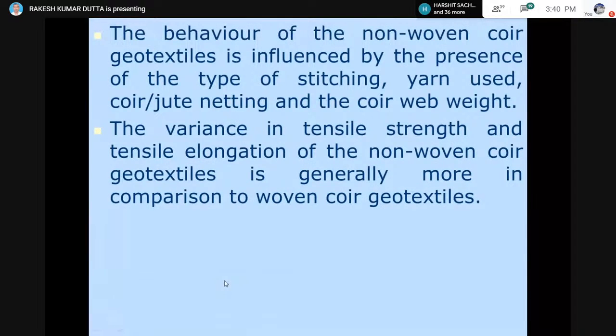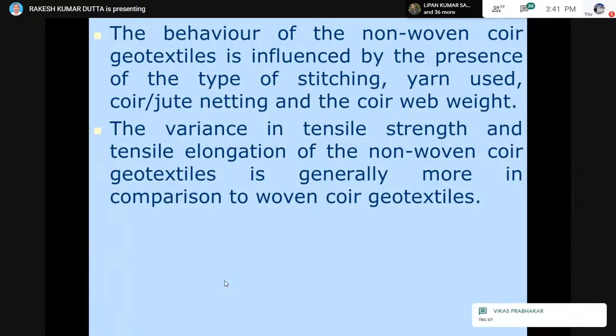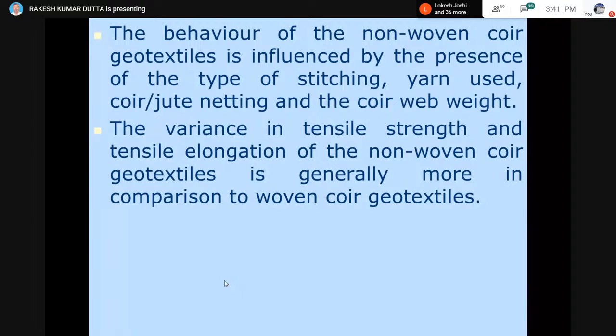The other conclusion drawn is that the behavior of non-woven coir geotextile is influenced by the type of stitching, what type of yarn we are using in stitching, whether a coir yarn or a jute yarn, or whether we are providing a coir netting or a jute netting on both the faces, and the coir web weight. Coir web weight contribution is very little, whereas the stitching and the yarn used for netting on both the faces, whether coir, jute or PP yarn, all these materials contribute to the strength of the non-woven geotextile.